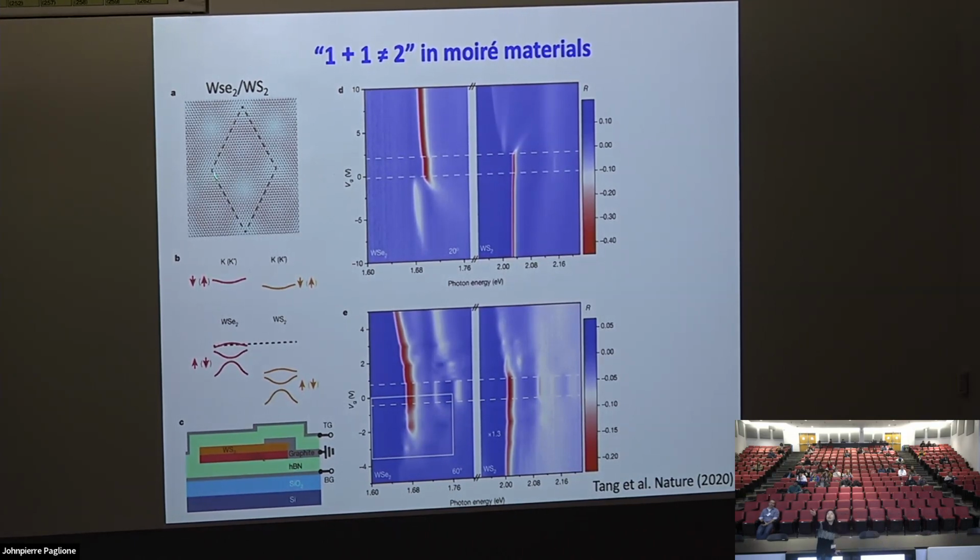If you just look at the underlying material, each has this honeycomb structure, and the central symmetry is broken. So you can do second harmonic generation from those layers. You come in with omega and you detect 2 omega.